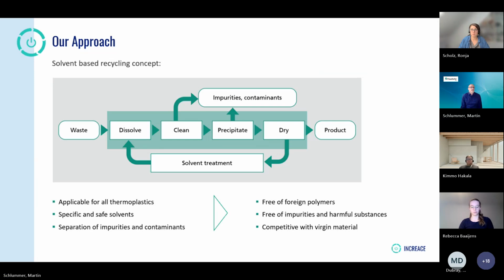Yeah, solvent-based recycling. Okay. Let me start with this concept overview here in the beginning. The basic idea is that you take that material that we've seen up front, either if it's a colorful one or it's the whitish one or the black one, doesn't matter at all. We put it into a tank, we put in some solvents, which is specific for the target polymers. We stir it, sometimes we apply some heat, and in the end we have a dissolved target polymer, and all the other materials in that feedstock are either undissolved or co-dissolved.